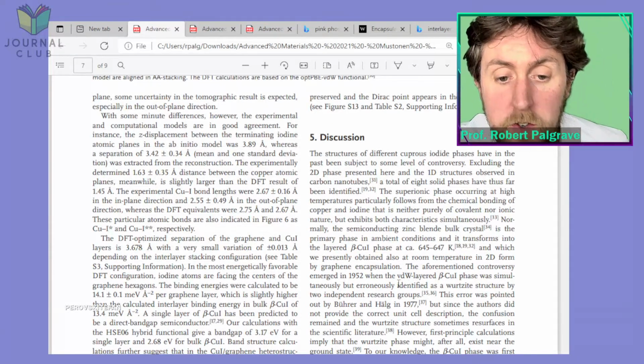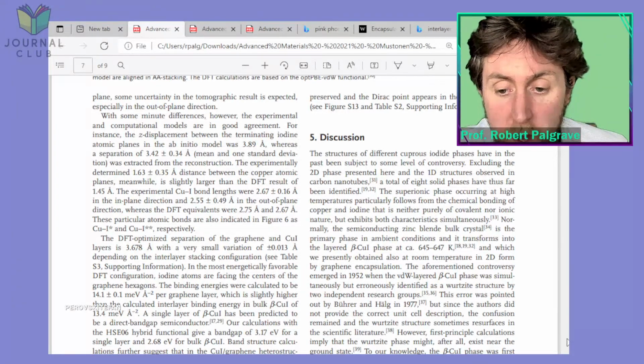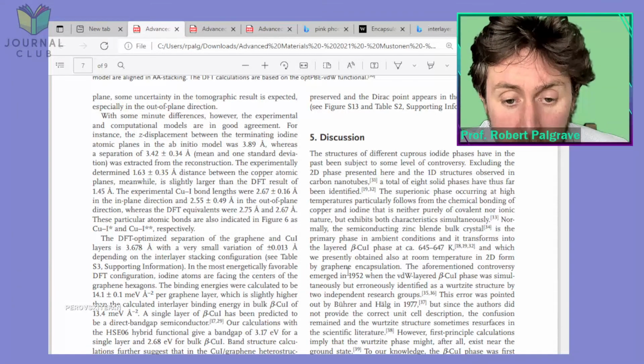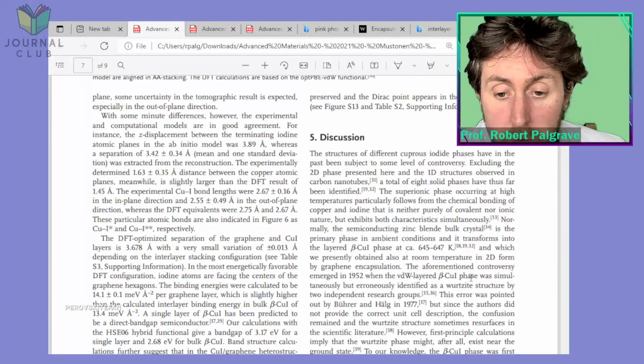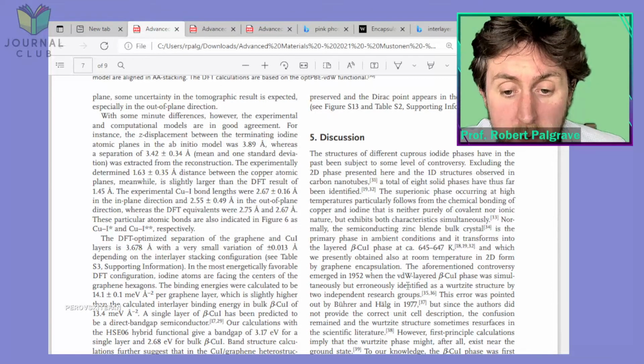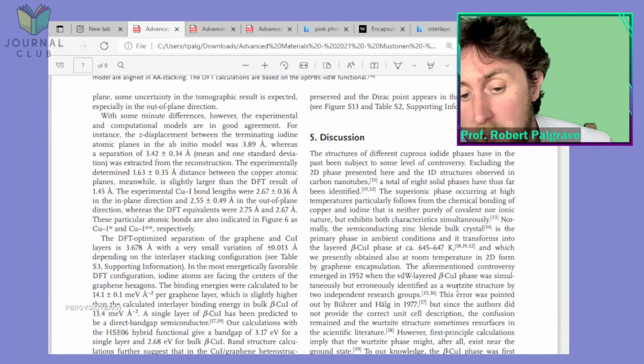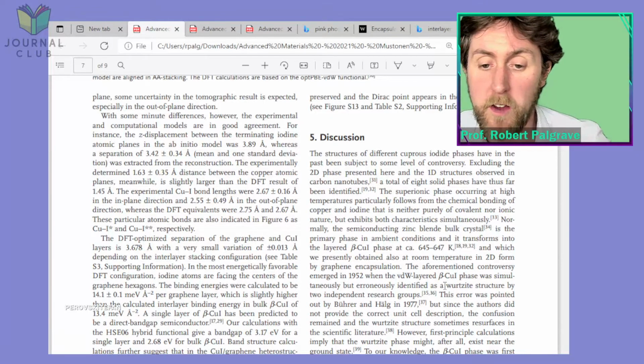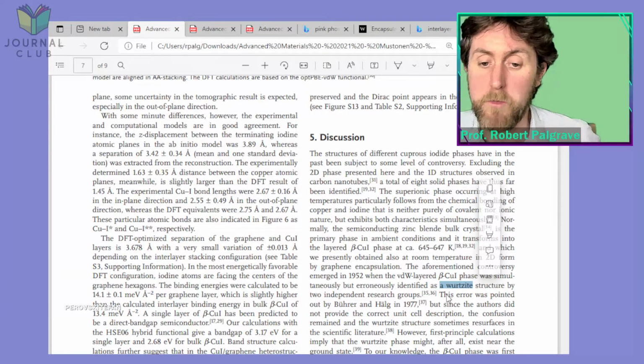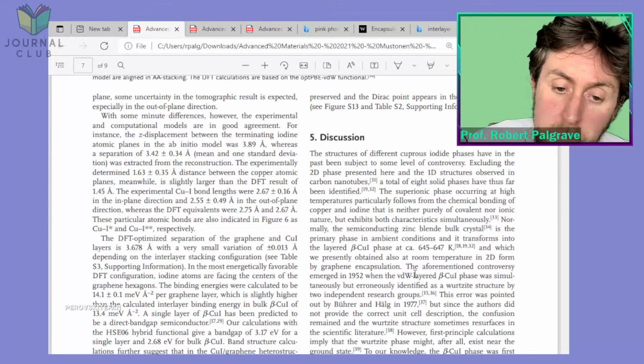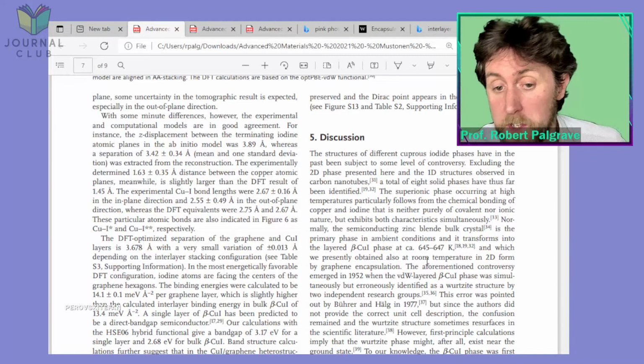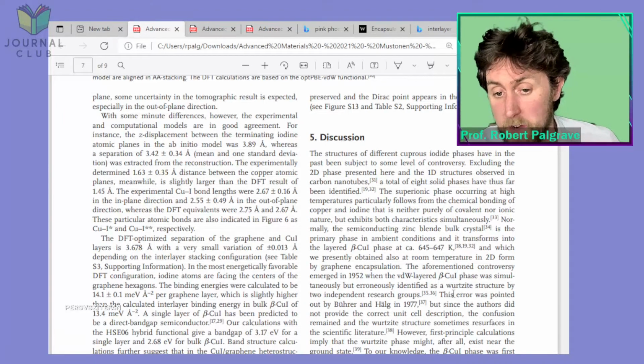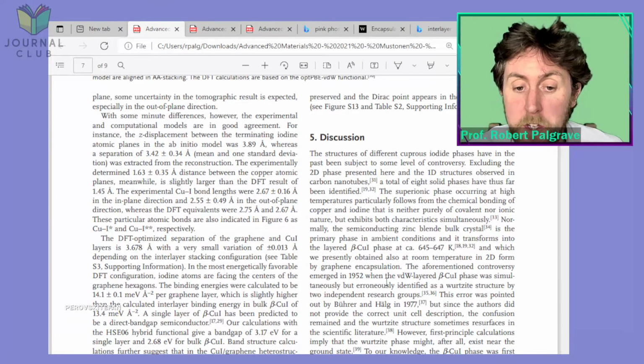The aforementioned controversy, all right, here we go, we have some history now. The aforementioned controversy emerged in 1952 when the van der Waals layer beta cuprous iodide was simultaneously but erroneously identified as a wurtzite structure. Okay, there we go, that's maybe what I was thinking of then, because I thought it was the wurtzite structure, which is maybe not that unusual a conclusion, because zinc sulfide, of course, adopts these two structures, the cubic zinc blende and the hexagonal wurtzite structure. Okay, by two independent research groups.